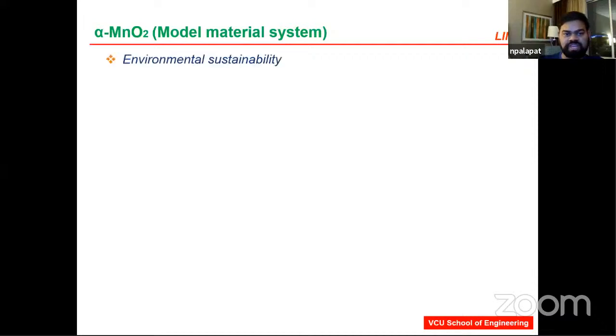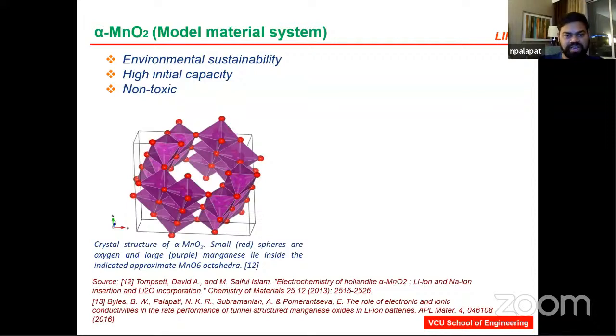In the sense it is very environmentally stable, it's readily and abundantly available, and moreover, the structure itself plays a very important role. So the crystal structure is alpha MnO2 with manganese lying inside. The big purple that you see is your manganese, and you have these octahedra, the oxygen, on the outer shells. The shape itself plays a big role in how this material system will be used in the future. I will talk further regarding this.